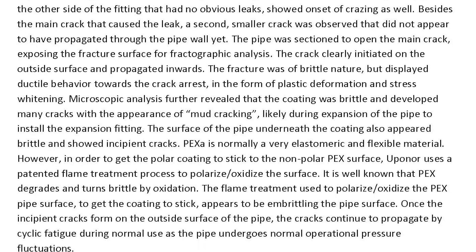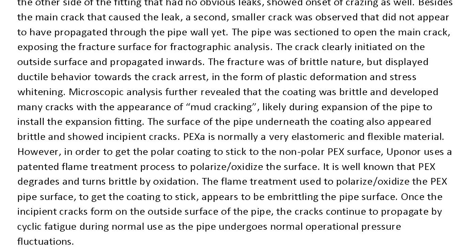The surface of the pipe underneath the coating also appeared brittle and showed incipient cracks. PEX-A is normally a very elastomeric and flexible material. However, in order to get the polar coating to stick to the nonpolar PEX surface, Uponor uses a patented flame treatment process to polarize and oxidize the surface. It is well known that PEX degrades and turns brittle by oxidation. The flame treatment used to polarize and oxidize the PEX pipe surface to get the coating to stick appears to be embrittling the pipe surface. Once the incipient cracks form on the outside surface, the cracks continue to propagate by cyclic fatigue during normal operational pressure fluctuations.